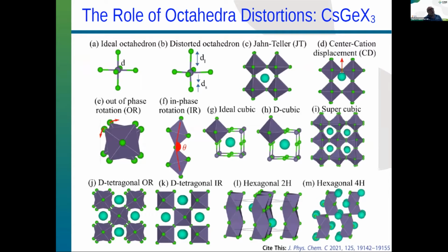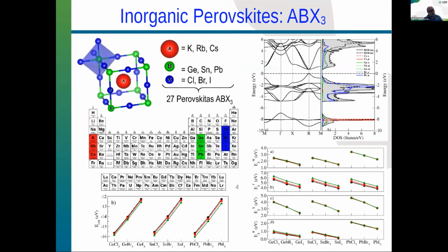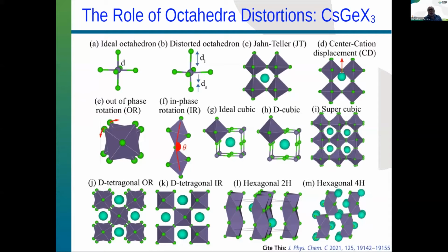Okay? In what sense? In the sense that you have a perfect octahedron. Before, in the previous study, we had a perfect octahedron. But now we investigate how distortions of the octahedron can affect the properties: electronic, excitonic, and structural properties. In that case, we investigate the Jahn-Teller effect, where you have 6 bonds around the bivalent cation, and they are equal in size, but then you make 3 longer and 3 shorter, and you create a Jahn-Teller distortion. As you can visualize here, this structure has elongated octahedrons, or you can make a displacement of the monovalent cation too, and then make a rotation out of phase or in phase of the octahedrons.